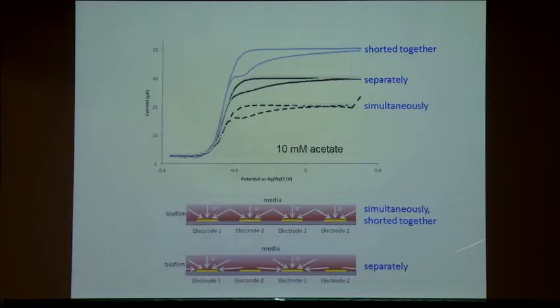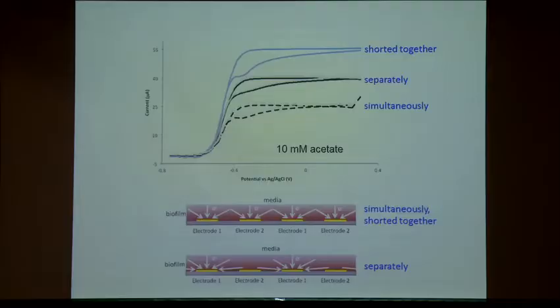This is the condition at which the biofilm is grown, and this is the thickness that was achieved by self-limiting. I don't do anything other than let the biofilm grow, and it achieves its own self-limiting thickness. And as a result, I get a certain current density per electrode. When I operate them separately, I'm actually getting more electron flux to each electrode, indicating that this last step was not the limiting step in growing the biofilm. And I don't know if I might have fumbled on that a little bit there.